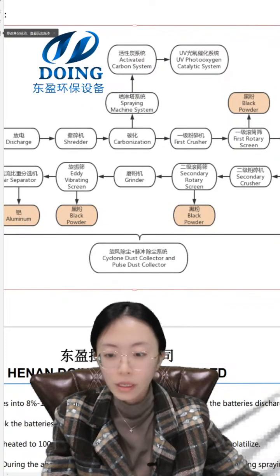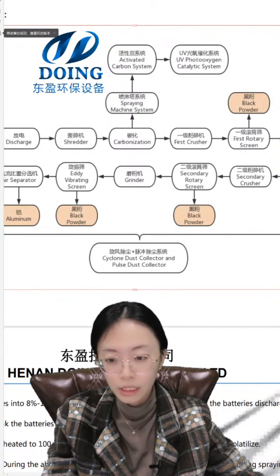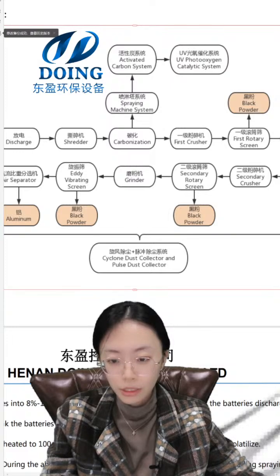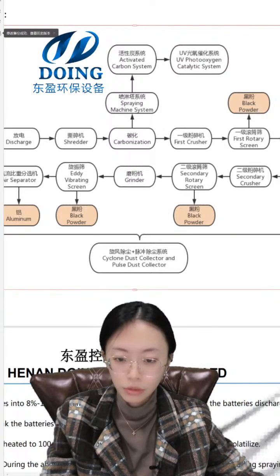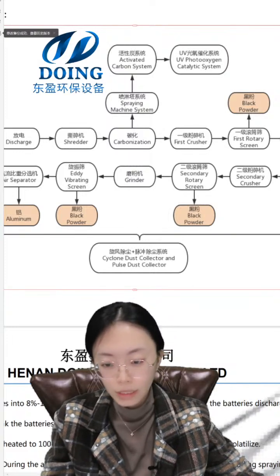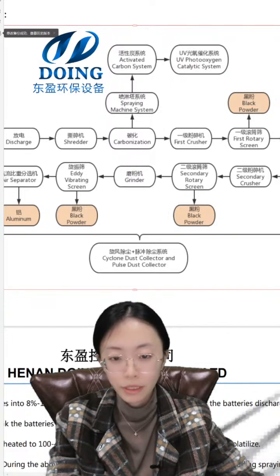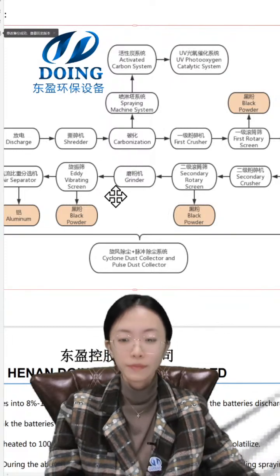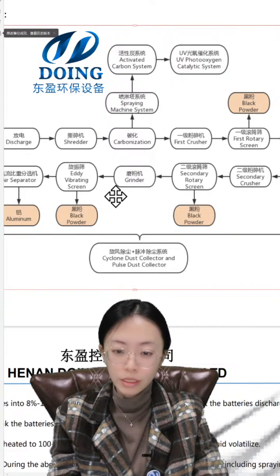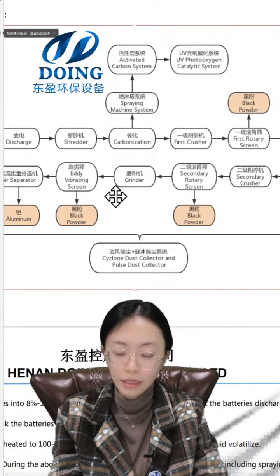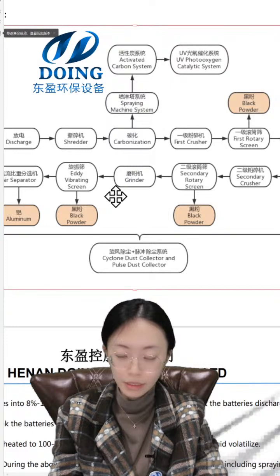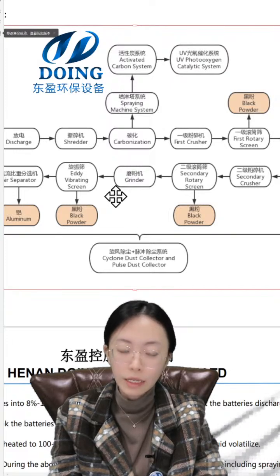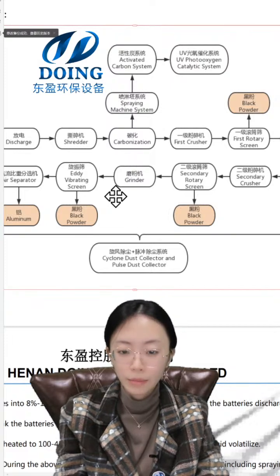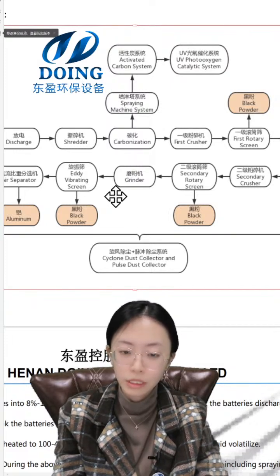Then this is the third crushing that we call the grinder. The grinder will grind the raw material, mostly the copper and aluminium, in granular shape, grinding the raw material to finer particles. Then the grinder is connected with the Eddy vibrating screen. Here, the Eddy vibrating screen is equipped with a 50 mesh screen in the upper layer and a 120 mesh screen in the lower layer. So a small amount of the black powder comes out of the lower layer, and the middle layer is the copper aluminium mixture. It will go into the next level for separation.